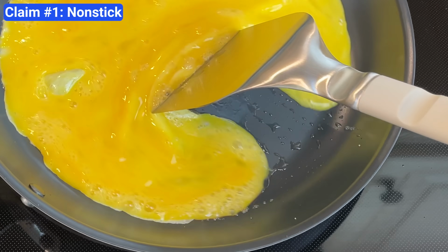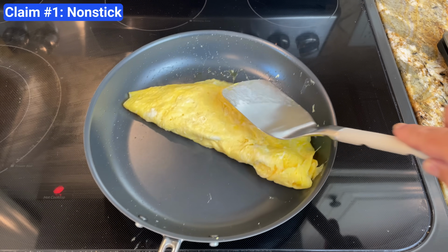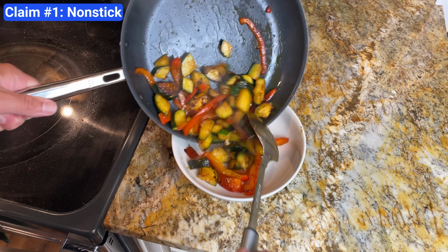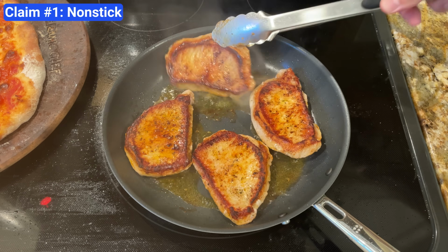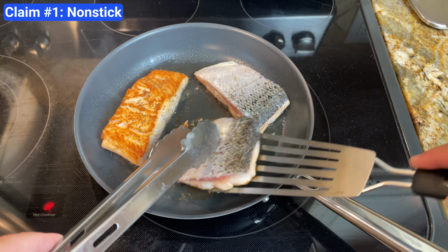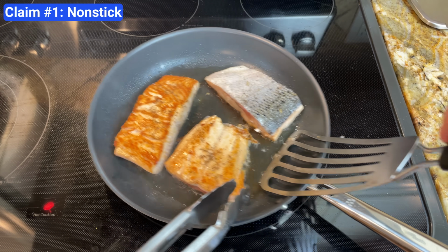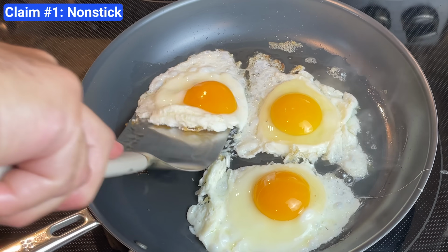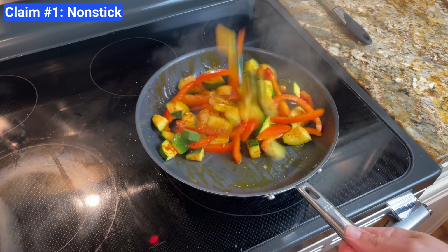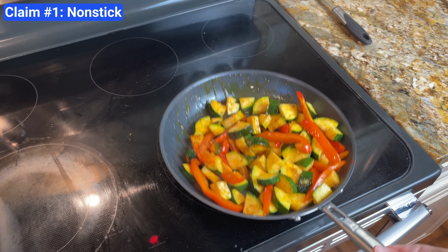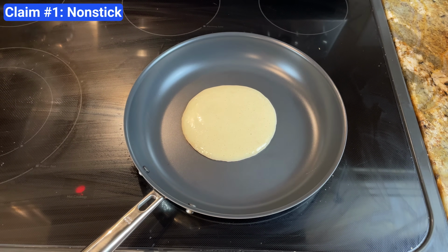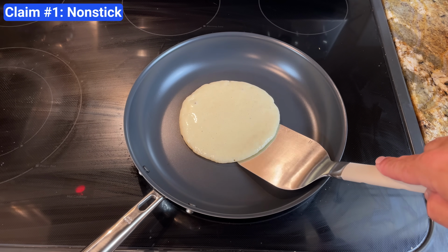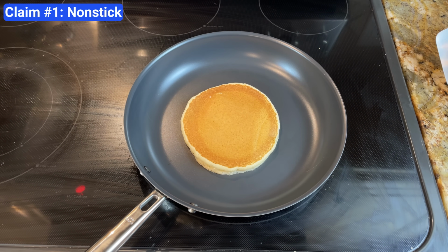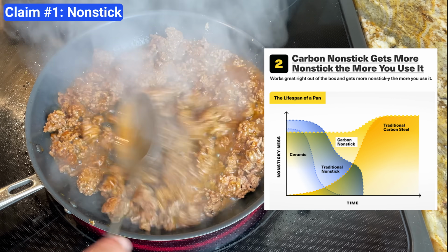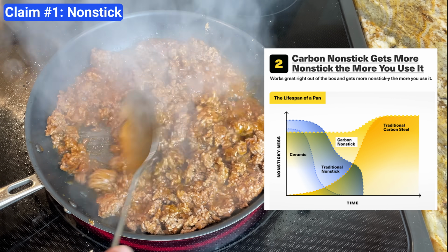When I cooked scrambled eggs and omelets, those released cleanly from the surface as well. I also cooked pancakes, vegetables, burgers, and pork without any sticking. The only exceptions were salmon, which started to stick, but it was probably because I tried to flip it too early, and a few eggs that stuck when I clearly overheated the pan. But overall, it performed like a well-seasoned carbon steel pan. You still need to grease it, and I wouldn't say it's as slippery as a brand new Teflon-coated pan, but it's noticeably easier to use right out of the box than traditional carbon steel. Misen also says that it will get more nonstick as seasoning develops over time, so I'll keep using it and see how that actually plays out.